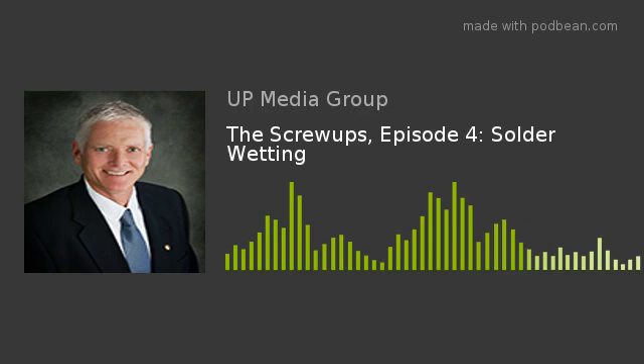So that's an easy way for us to know we can start to work on the one thing that we can manipulate in the process, profile, to enhance wetting. Then the engineer and our tech team will busily work together on profiles, and it might not come as a surprise that if a hot, short heating cycle with a soldering iron breaks down oxide, it's our experience that a hot, short profile will often improve outcomes as it relates to wetting. It'll improve wetting as a matter of course, and for two reasons. The first reason is that you don't reoxidize the components in the reflow oven. Adding thermal energy to a PCB increases the oxidation rate of the alloys that are on the board.